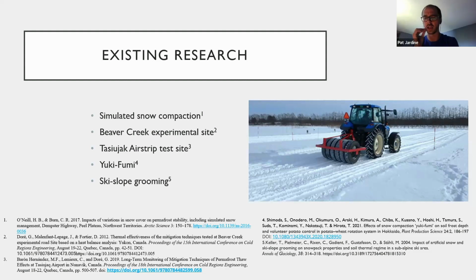Next up is the Tasiujaq airstrip test site. They didn't mangle that too bad. Here, a variety of techniques were also tested, including heat drains, air convective embankments, and widened embankment slopes intended to limit snow accumulation. Over 10 years, the widened slopes outperformed the other options and caused the permafrost to degrade under the shoulder by over 1 meter, while the reference site degraded by over 3 meters. So it was extremely effective and very promising for snow management.